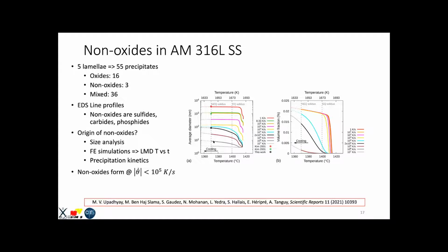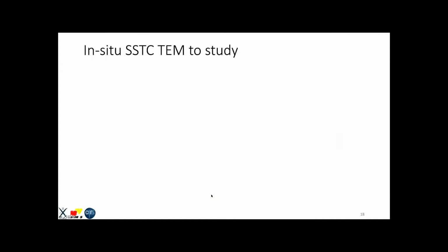Above that, it's quite small in diameter and very little in volume fraction. During LMD, we see temperature rates that are typically of the order of 10⁵ or less. But during SLM, we have temperature rates that can go higher, up to 10⁶ or 10⁷. That could be the reason why we do not see them in SLM. So this work we recently published in Scientific Reports, and you can find it over there.